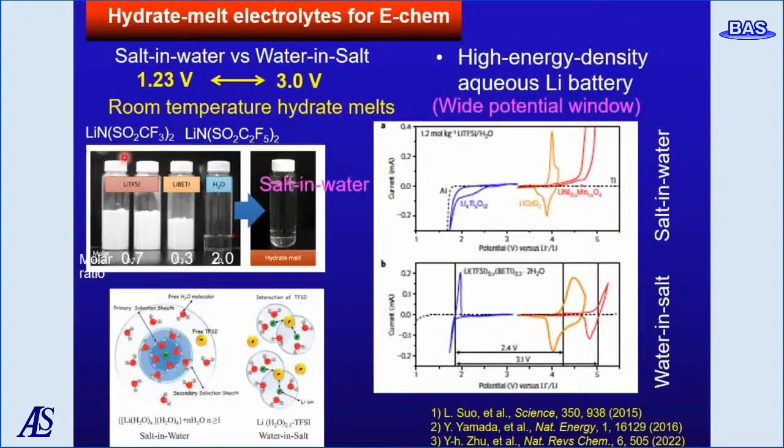Here, what is used is the molten hydrate made by mixing lithium bis(trifluoromethanesulfonyl)imide, lithium bis(pentafluoroethanesulfonyl)imide, and water in precise molar ratios. Once mixed, they can become a transparent liquid.